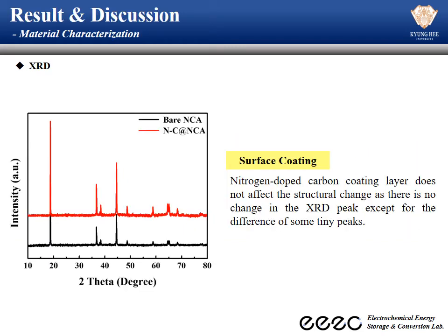In order to compare the structural properties of bare NCA and N-C@NCA, the XRD analysis was measured first. As a result of confirming the XRD pattern between bare NCA and N-C@NCA, it was confirmed that the nitrogen-doped carbon coating layer did not affect the structure change of the NCA, as the XRD peaks were the same, except for a very small peak difference.